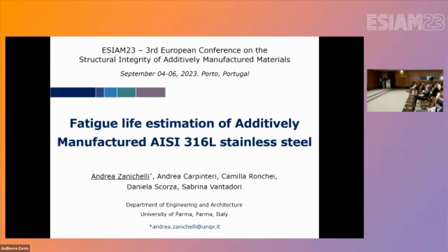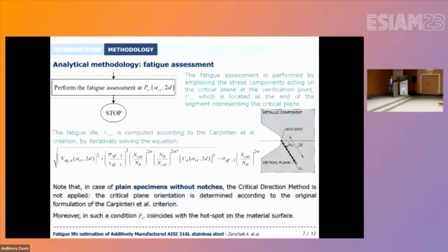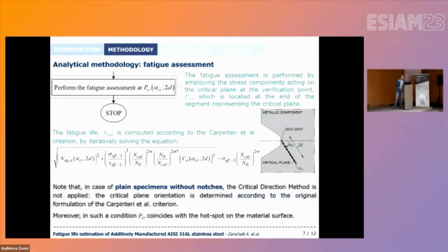Yeah, yeah. Actually, in this case, we applied it to this material, but we already applied this procedure to many different material types in the field of fracture and fatigue. And actually, we take into account the two different slopes of the SN curves in the computation of the fatigue life, because as you see, the exponents m and m* are the slopes of the SN curve under normal and shear loading. So actually, not for AM metals, but for conventional metals, we have already applied it to different types of materials, also with different slopes in the SN curves.